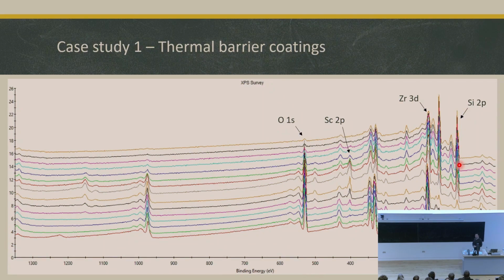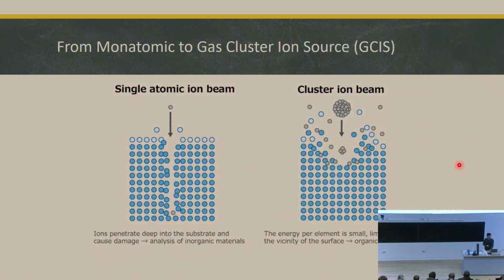So researchers really can make the films and stack them together, but it's XPS which can quantify and measure whether they have the right films with the right thickness. There are two ways of etching the surface. One is called a single atomic ion beam from argon. You can imagine it's a bullet that can penetrate deep into inorganic material. But for organic materials, we use a softer cluster ion to gently etch the surface because organic materials are more fragile.